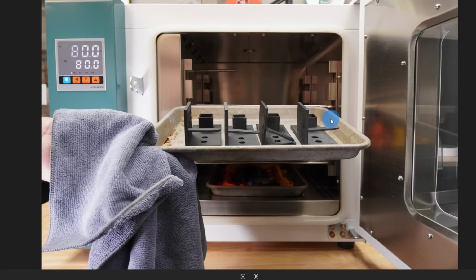So in order here, this front one is PC Max, Polymaker PC Max. The next one is Polymaker Silk PLA. The third one is Polyterra PLA, and the last one is the High Temp PLA. The High Temp PLA was annealed 110 degrees, 30 minutes. And at 80 degrees, the silk was starting to fail. The Polyterra was sagging a little bit. The PC Max was actually going up.